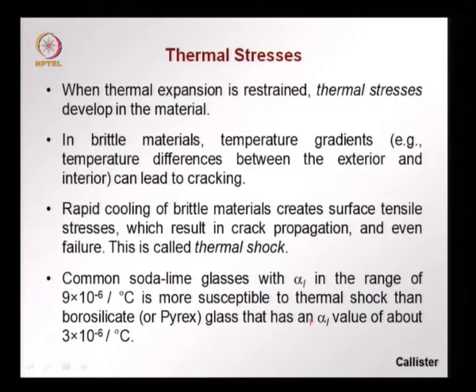whereas the inside is still hotter. This creates tension on the surface, because you can imagine the surface is trying to contract, the inside is not allowing it to contract, and the only way that the material can contract is by cracking. So, this creates crack propagation through the material and can even cause failure, and this is called thermal shock. And this is something that might have occurred to you when you have say a glass recipient which was in hot conditions and suddenly you pour cold water into it, the glass can crack. Not something that you should try out, but this is something that could occur, and the phenomena that causes this failure is called thermal shock.